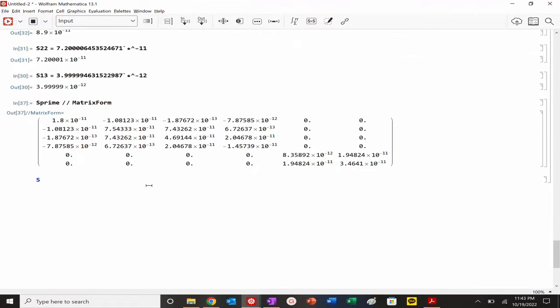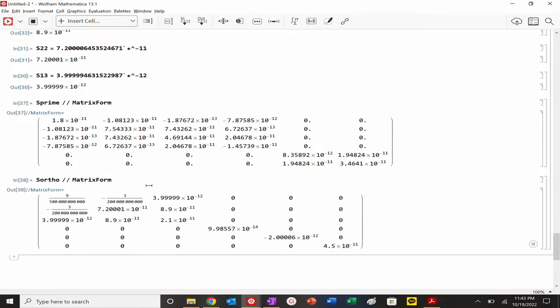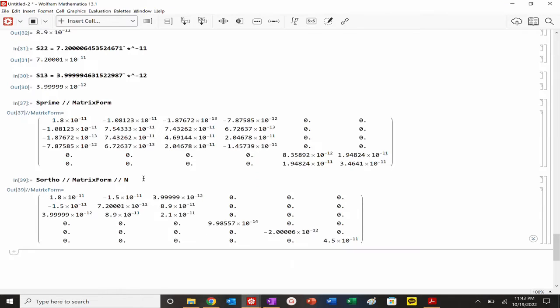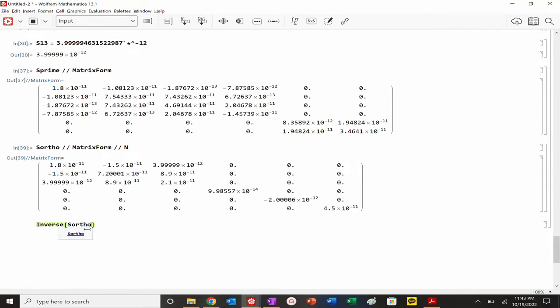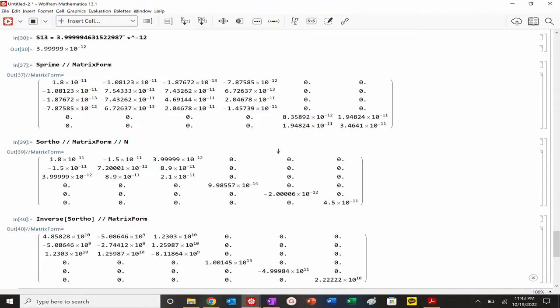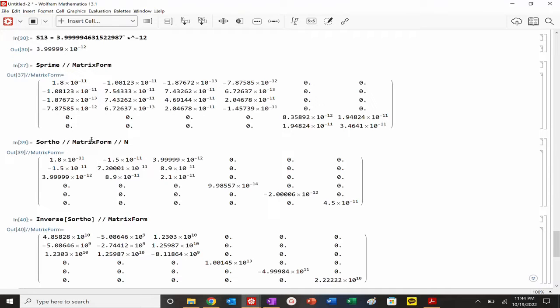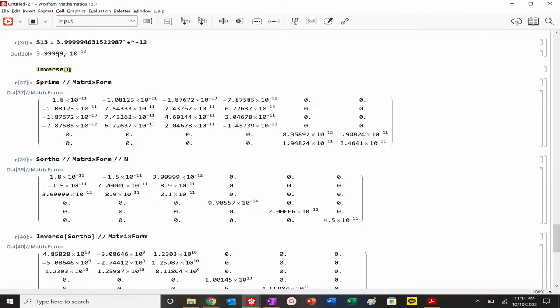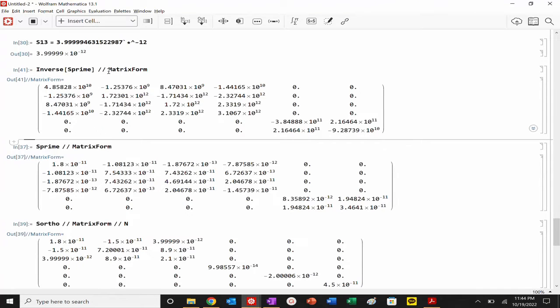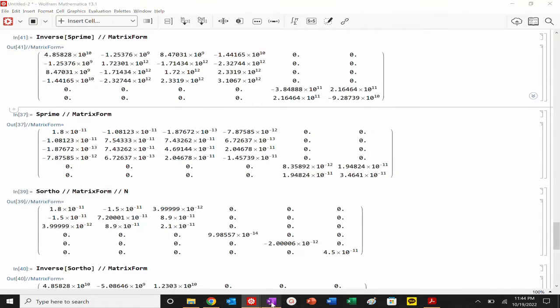Now we can look at S_prime and S_ortho and their inverses. Stiffness is simply the inverse of the compliance tensor. We need to rotate back to the original coordinate system: sigma_OG = T_stress_1 · sigma_new with counterclockwise rotation (positive theta). Similarly for the strain tensor.